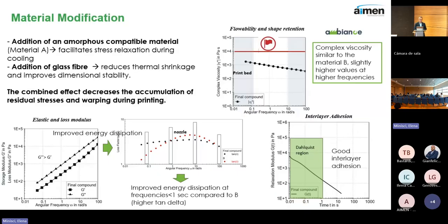Next, if we go to the bottom left, is the curve where we are showing the two moduli, the G prime and G double prime, so the storage and the loss modulus. As you can see here, I don't know if you can see well in the presentation, I hope it's big enough, but in the whole range of frequencies, the loss modulus is over the storage modulus. This indicates a viscous nature of the material, which is very good for dissipating stresses, for preventing warping, and also helps the interlayer adhesion.